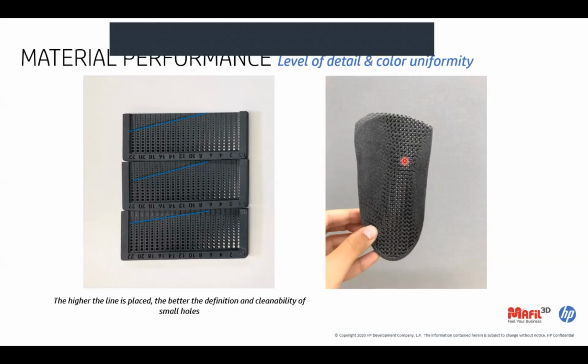and you will achieve such a nice clean part. If we take a look at the picture on the left side, you can see the level of detail I was talking about. You can see different diameters of the holes over there. The higher the line is, the higher the level of detail we achieve. For elastomeric material, because the behavior is different when comparing with the PAs or with polypropylene, the dimensional accuracy is not on the same level, but as you can see over here, we did quite a good job in terms of accuracy and level of detail, because most of the small holes over there are visible and open. This is something I would like to pinpoint when talking about the TPU.